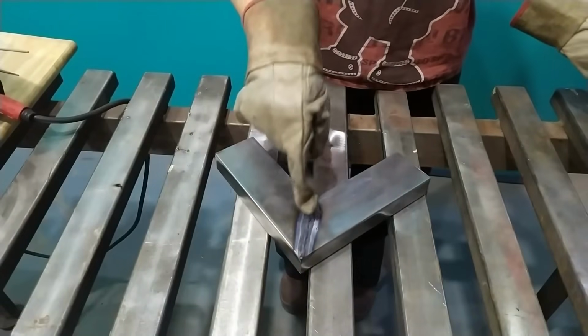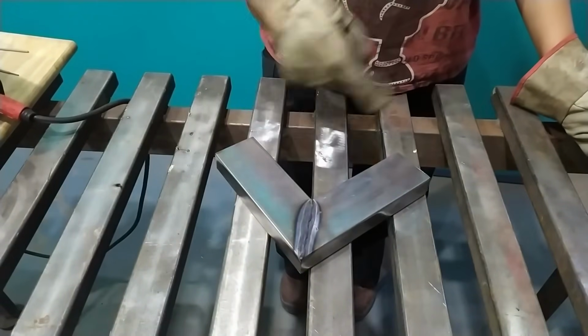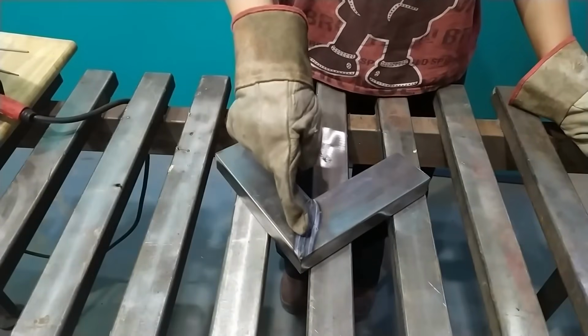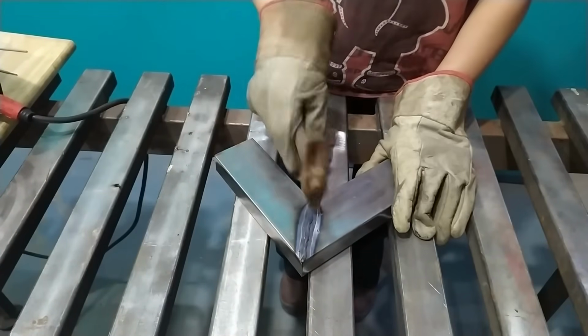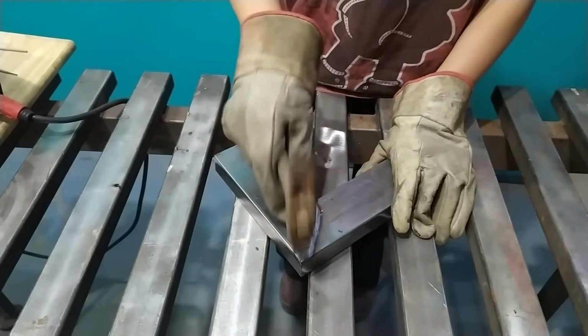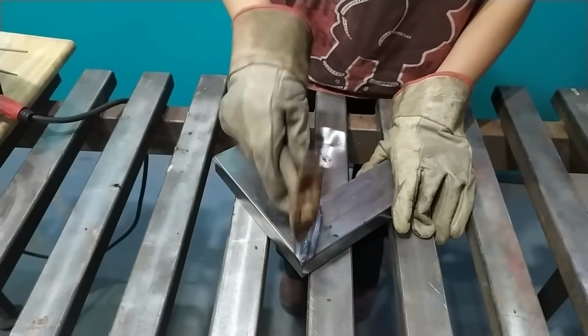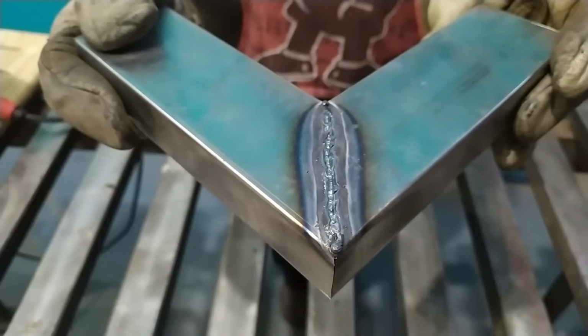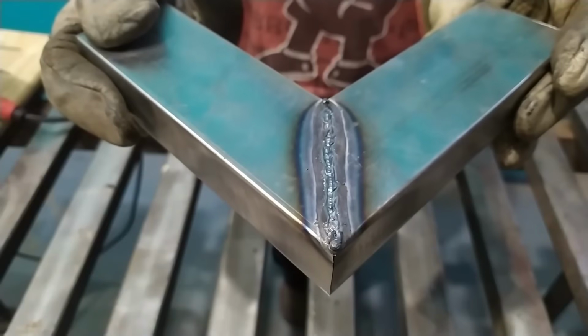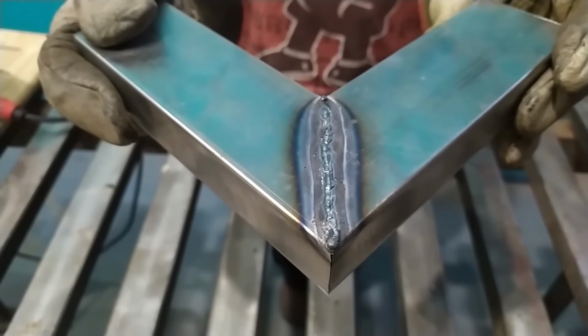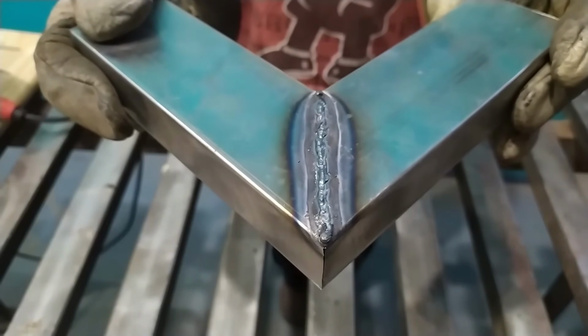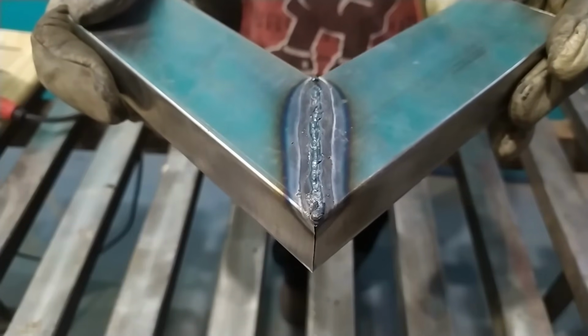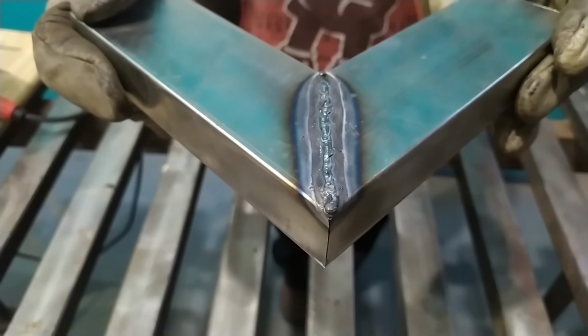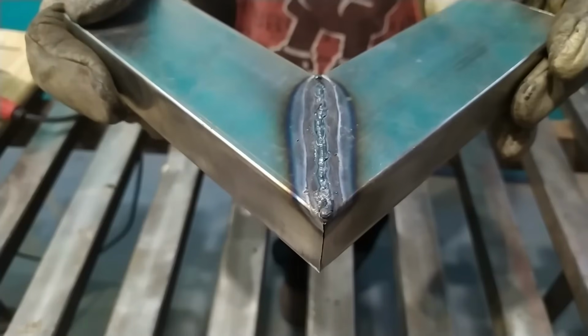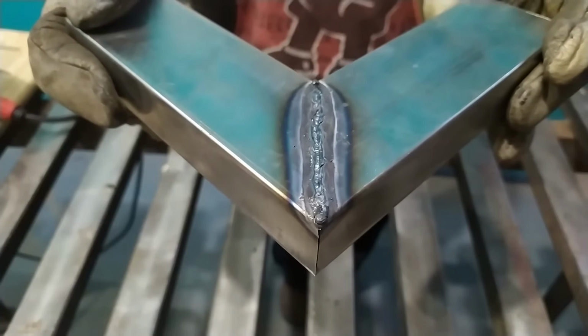And that's how you get a continuous weld with an electrode on a thin metal section. In direct polarity, the slag will be harder to remove, but with a few taps it comes off. As you can see, the bead itself isn't very aesthetic, but in these cases, we don't need it to be aesthetic. We need it to be a strong and sturdy bead, and in this case, that's what we achieved.